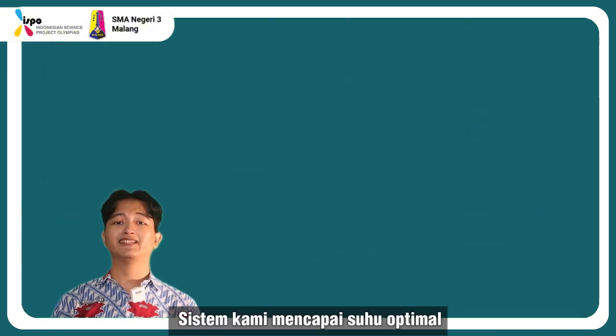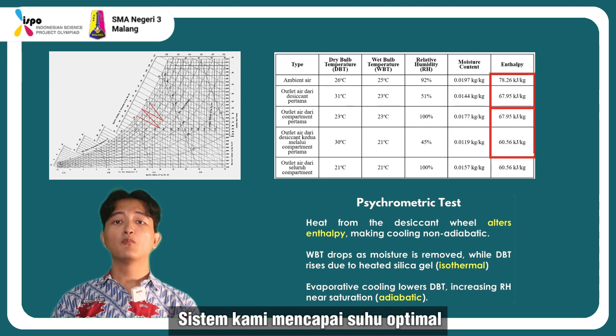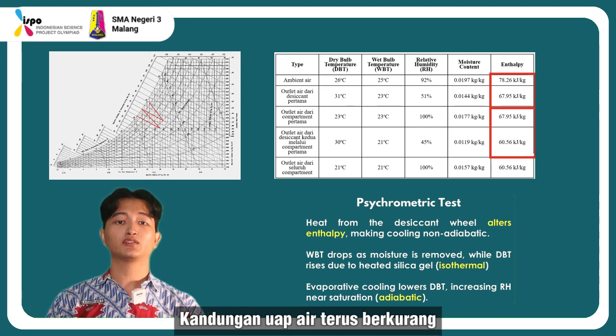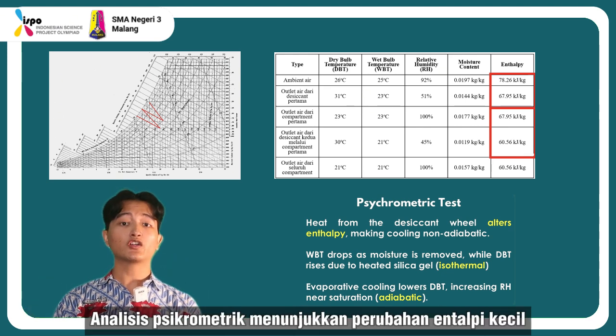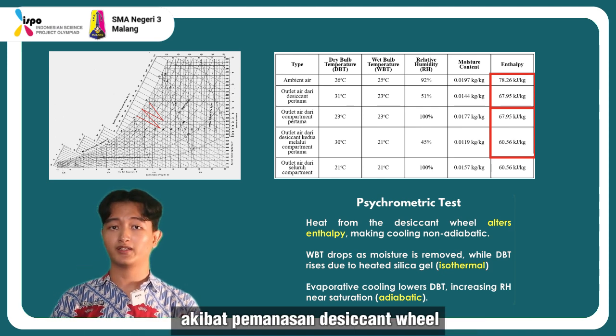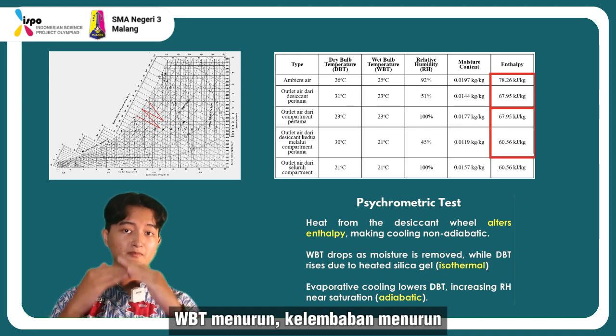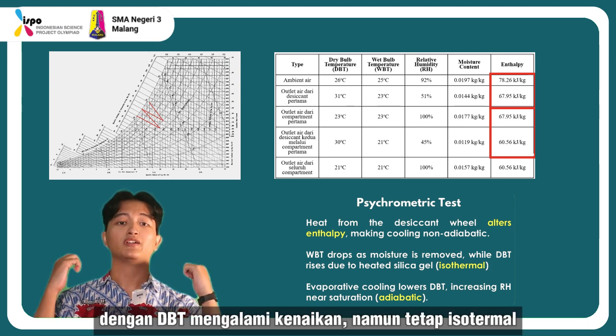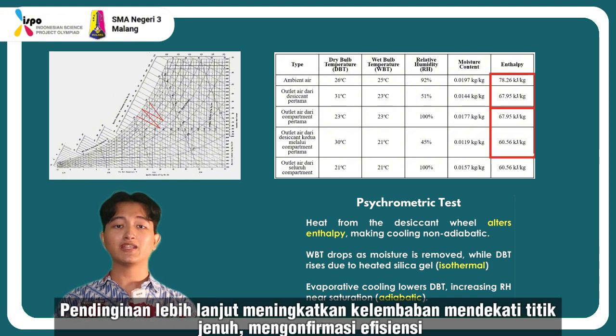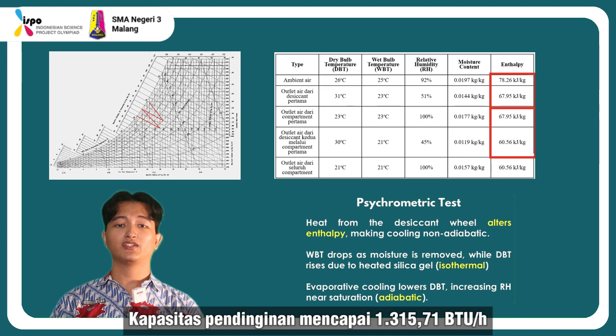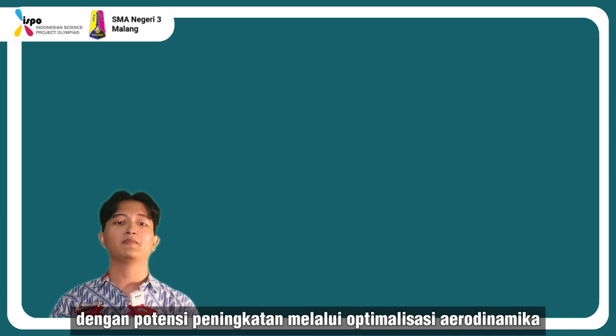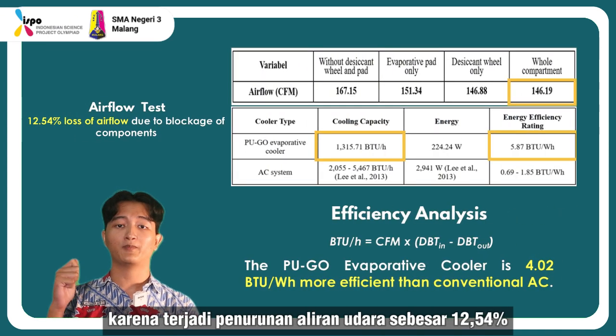It is shown that the system achieved optimal temperature. Moisture content continuously decreased due to isolated airflow. Psychrometric analysis shows slight enthalpy changes due to heat from the desiccant wheel. It lowers WBT, reducing humidity, while DBT rises slightly but remains isothermal. Further cooling increases humidity near saturation, confirming the efficiency. Cooling capacity reached 1,315.71 BTU per hour, with potential improvement through better aerodynamics as airflow dropped 12.54%.